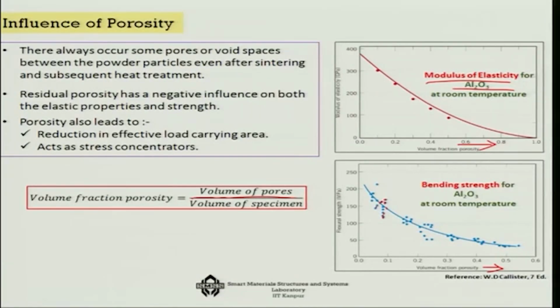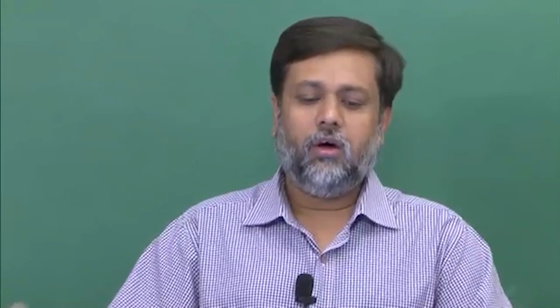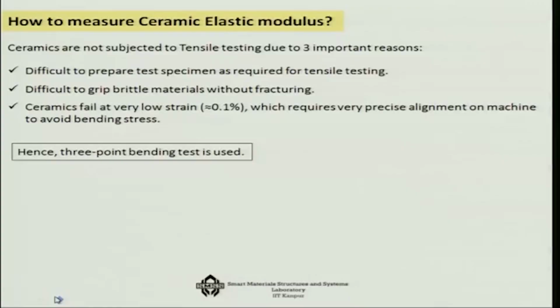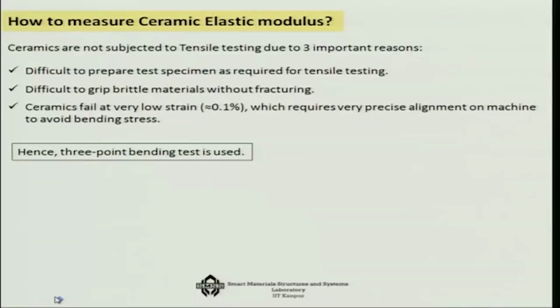And how do we measure the volume porosity? Well, there are several ways. One is called the BET technique, by which we subject these ceramic materials to absorb a gas, and then depending on how much gas is absorbed, we find out the porosity of the particular ceramic sample. Now, how do we measure the ceramic elastic modulus? It looks like a very trivial question, but it is not trivial at all. Why? Because when you have to make a particular sample for elastic modulus determination, say for example a steel sample, you have to make a certain necking arrangement. So, this is a dog bone shape of the sample.